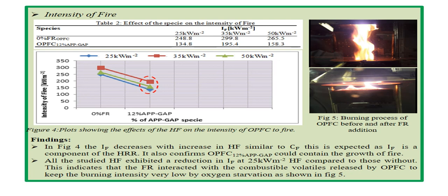As you can see in the picture, this is the burning intensity of the control, which is without the flame retardant, and below it's a picture showing how low the burning is. That is, the combustible volatiles have been reduced and the fire is almost getting extinguished.